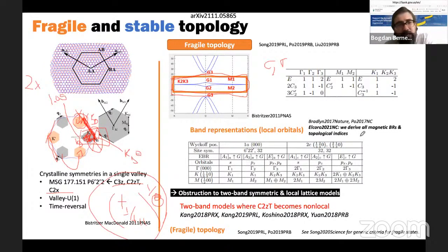To make a long story short, we know what all the eigenvalues of the atomic limits for all the bands in all the symmetry groups are. So what do I mean by that? Remember that I said that if a flat band comes from localized orbitals, then I can understand why it's flat. The problem is that once you tell me which localized orbitals I have, I can tell you exactly which eigenvalues the bands have in momentum space. And it turns out that none of the eigenvalues of any localized orbitals in this space group match the eigenvalues of these bands. Hence, the bands have to be topological.